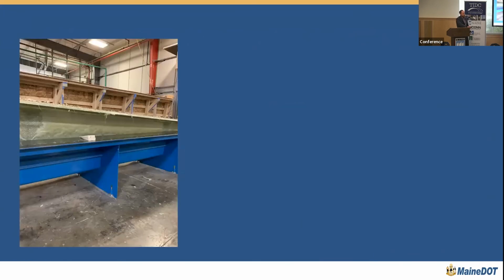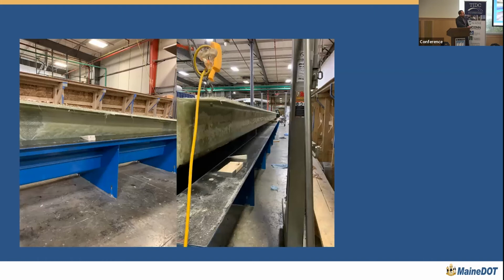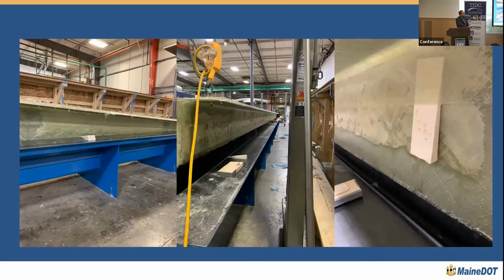So, airing a little bit of dirty laundry here. Show you the extreme of what can be repaired for non-conformances. During one of the UTC test girders, a little bit of vacuum infusion issues with the new form at AIT. As you can see, it's not supposed to look like that. Big old pillow, wrinkly. That is complete non-wet out and non-compaction. That was just one layer, shoved a piece of plastic in there just to kind of see. Rather substantial layup issue. This is not a DOT-bought girder. This was one that was going to be set for testing, which makes this perfect.